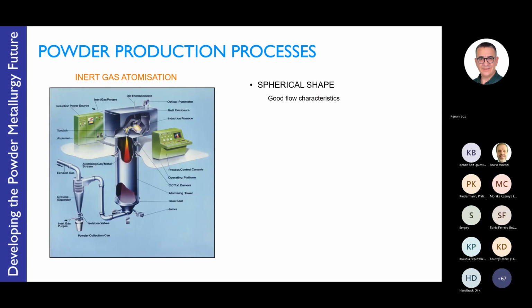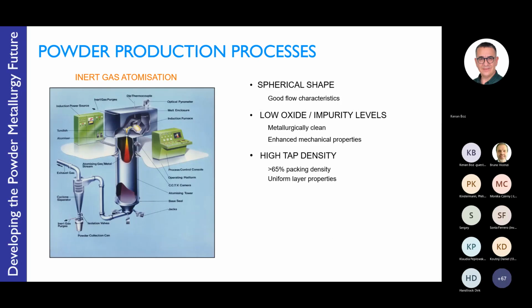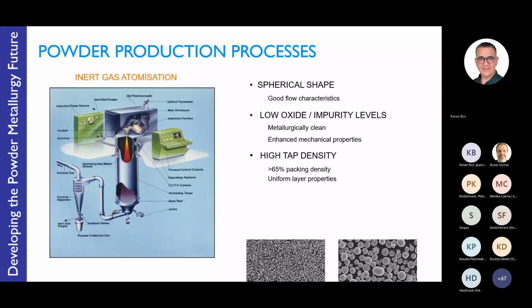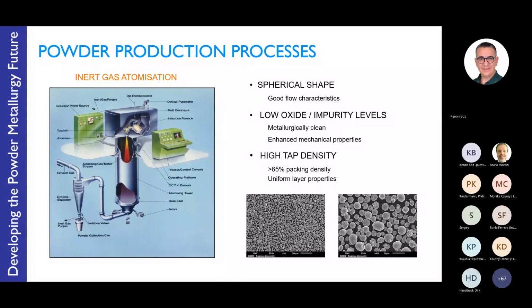So as I mentioned, the gas atomized powders have a spherical shape which imparts good flow characteristics. Because of the melting enclosure and the relatively clean process, metallurgically clean, it provides good performance when it comes to mechanical properties. The powder has a broad normal size distribution, as you can see from the diagram here, and a very spherical shape, a range of different sizes of particles, and that provides a good tap density or packing density. And that can be very advantageous when it comes to additive manufacturing to provide uniform layers with good flow characteristics.